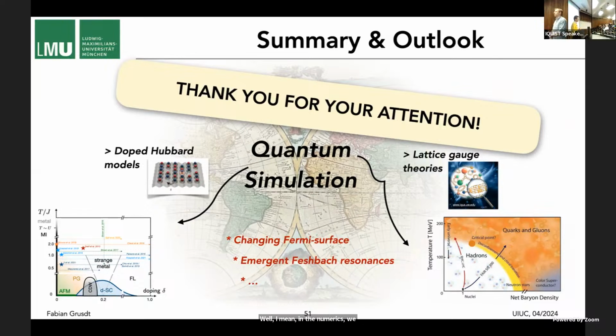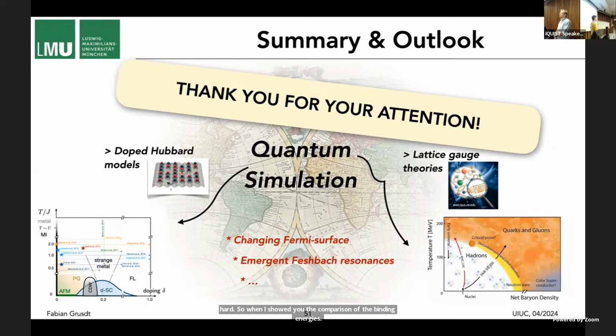Experimentally, measuring these gaps is kind of hard. When I showed you the comparison of the binding energies, we relied on an effective model that we fitted to the data to get the experimental binding energy. In principle, there's one proposal, for example, to take a ladder, split it in two parts, and have a tunnel junction between them. Then by measuring the oscillation frequency of pairs, you can directly measure a pairing gap. And for a spin gap, you would do spin flip type spectroscopy. Then you could compare and distinguish them. So experiments have not directly measured these gaps, unfortunately. That would be cool to see. It's in principle doable, but not so easy, I'd say.